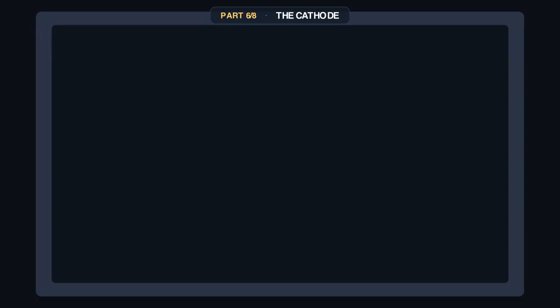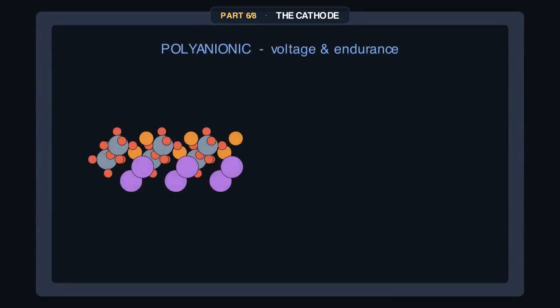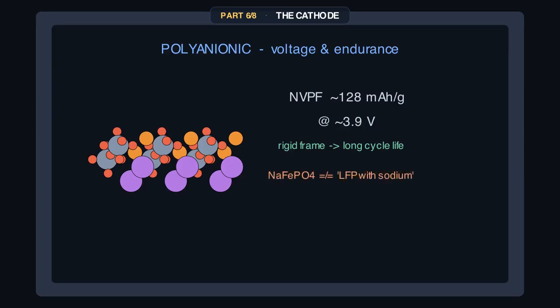Branch 2, polyanionics, the voltage and endurance branch. Sodium woven into rigid phosphate frameworks. Lower capacity, only about 128 mAh per gram, but look where it sits, nearly 3.9 volts, in a frame that barely moves as sodium comes and goes, so the cycle life is superb. Remember, energy is capacity times voltage, so high voltage rescues the modest capacity. And here's a myth to kill. You cannot just make sodium iron phosphate as a copy of lithium's LFP. The useful form is metastable and stubborn to make. The form that grows naturally, maricite, has no channel for sodium at all, electrochemically dead. Sodium had to invent its own hosts.